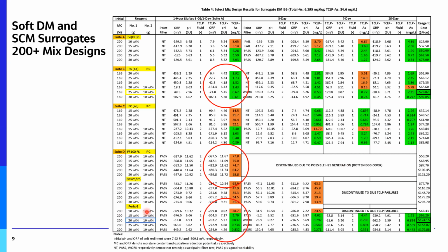Down here, we have ferrics, which is actually the dry powder version of ferric sulfate. And we began taking a look at those combinations. And again, we're very good on our pH, very good on our leach, except for the lowest dose. So we got rid of that one, but all these other ones tended to work out fairly well. At the end of the day, what we ended up recommending were the 2 black boxes on the right-hand side.